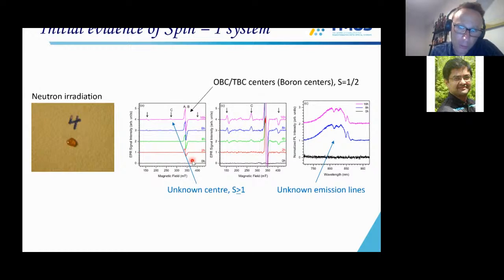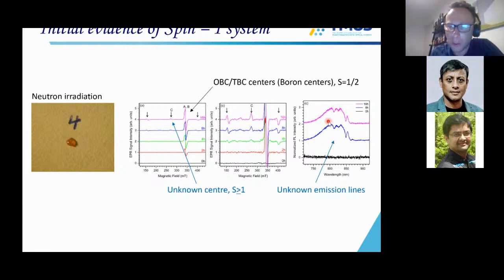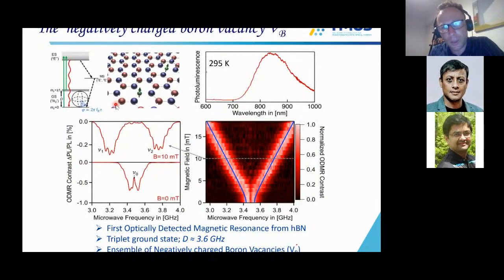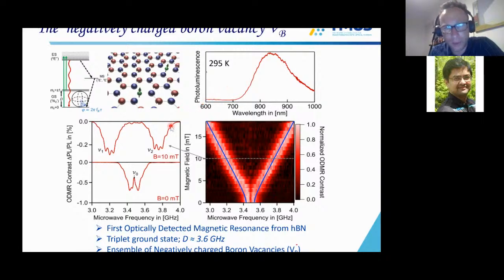And what we noticed is that with high doses, we saw a new line. And this new line appeared with a spin 1, not a spin half. And when we looked optically, we saw a broad emission around 800 nanometers. Now, please ignore the peaks. We realized later on this is just an artifact of the spectrometer. So it's just a broad emission. But what was important is when you do ODMR on this broad emission, you actually see a beautiful response.